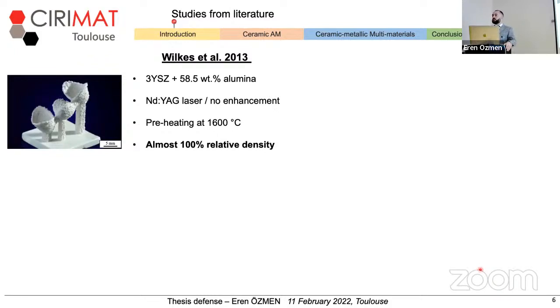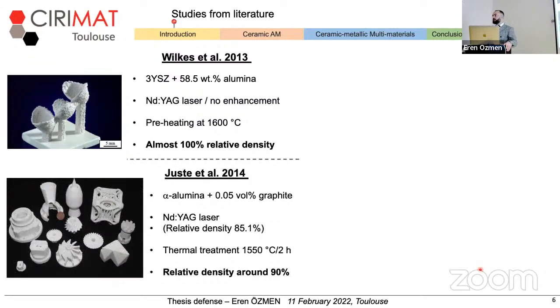For example, Wilkes et al. in 2013 aimed at reducing the thermal gradients between cooling and heating by introducing a preheating system in their PBSLP machine. The preheating was applied at 1600 degrees to the building platform, and the final pieces with almost 100% relative density were obtained. In another study carried out in Belgium Ceramic Research Center, alumina powder was combined with graphite as an absorbency enhancer, and after the PBSLP process, the density of the pieces was around 85%. Then a thermal post-treatment was applied to the pieces, and relative density was increased up to 90%.